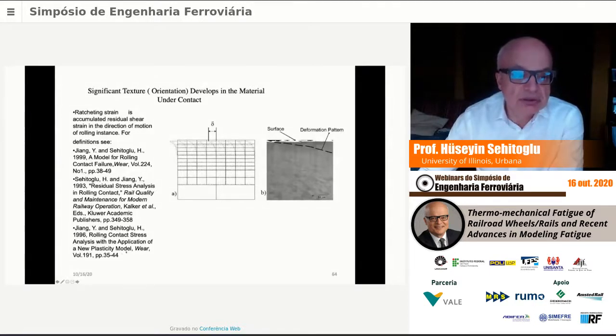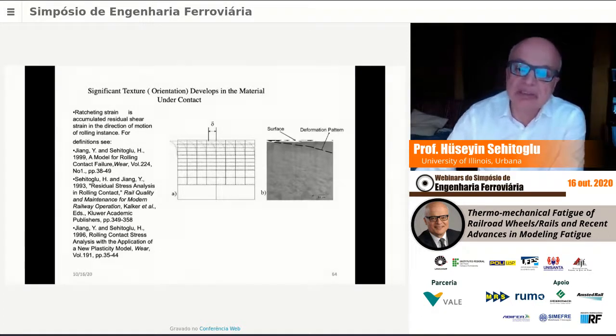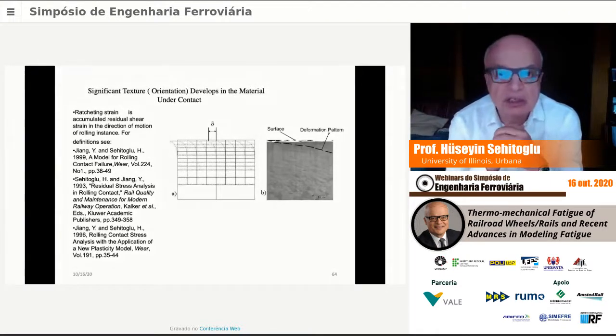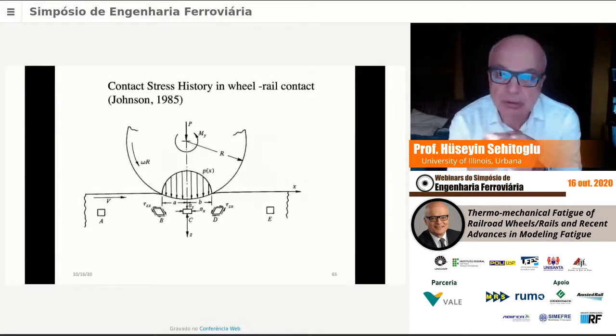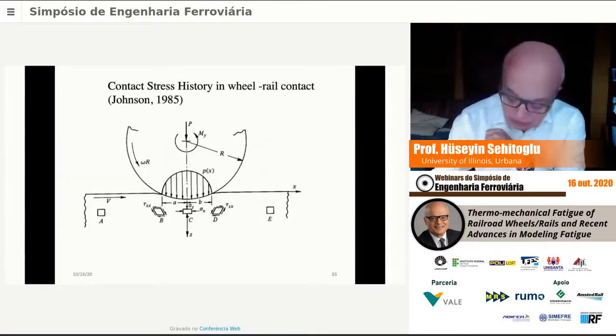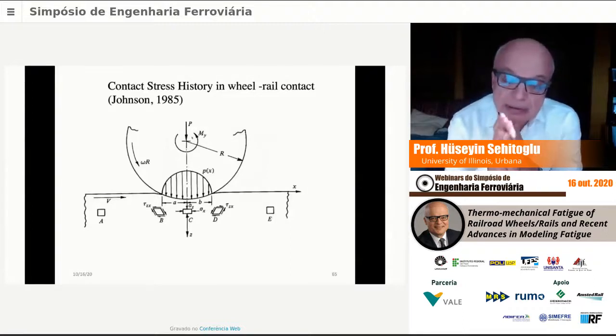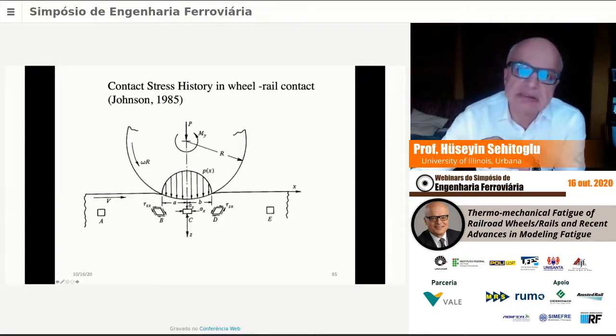Probably this one, which we call model for rolling contact failure and the rolling contact analysis with the application of a new plasticity. So the key thing here is to have a good constitutive model that predicts this ratcheting. You could do that in a semi-analytical way, or you could do it in finite elements. But even if we use finite elements, we need the right constitutive model, which does not exist in commercial codes. But we have a model that we implemented in the codes. I want to mention that this, of course, is an important problem, especially in rails. And the fundamentals are probably given best in this book by Johnson.